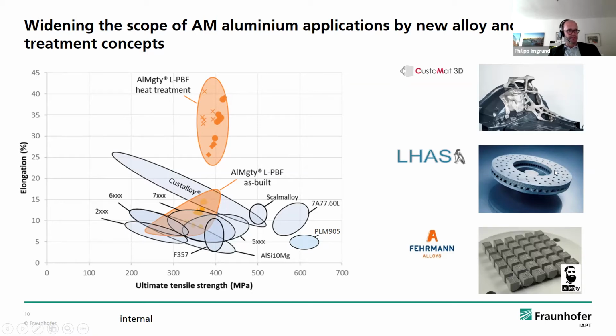But also we're looking at very high strength materials, which is this PLM 905, very high strength for, well, we sacrifice ductility, but it's also a brake disc application here. And together with a company in Germany here, Fehrmann Alloys, we're also developing the Almighty alloy, which provides elongation up to 40% after heat treatment on a very specific tensile strength area of around 400 megapascal. So this just shows a variety that you can do with material science. As a material scientist, I have to show this, and I hope it finds your interest to some extent.